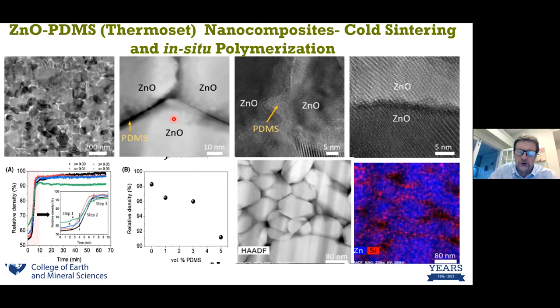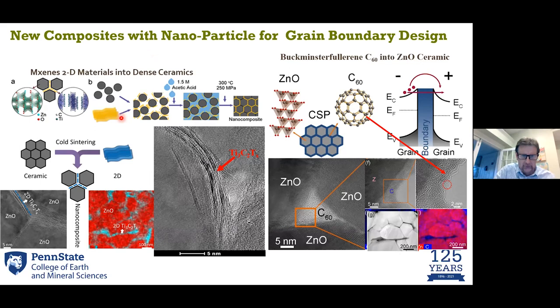So it opens up the enormous way of which various different aspects of material science can interact within this processing. Not just polymers, it can also be nanomaterials. Here you can see some nano, so-called 2D materials. Penn State is very, very big in 2D material. We've got over 50 faculty working in nanomaterials with these 2D type morphologies. So here you can actually disperse around your ceramic nanomaterials that are 2D in shape around each of the individual grains, and then sinter this whole thing together and trapping that in all at this sort of 5 nanometer scale. Over here, we've done the equivalent with the old-fashioned buckyball, right? Very, very similar. You see the buckyballs on the grain boundaries.